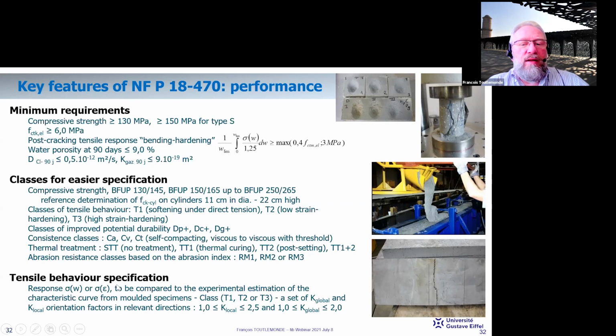It was clarified how to specify the tensile behavior, which is quite important since it's one of the key aspects connecting the project to what must be checked in the material. It has to be characterized by a stress-crack opening or stress-strain curve, compared to the experimental estimation of the characteristic curve from molded specimens.